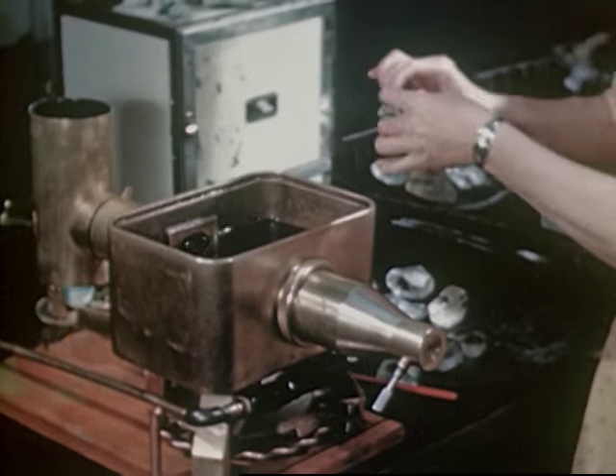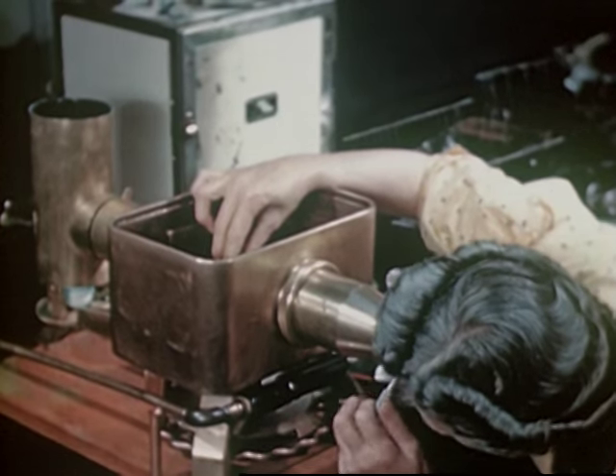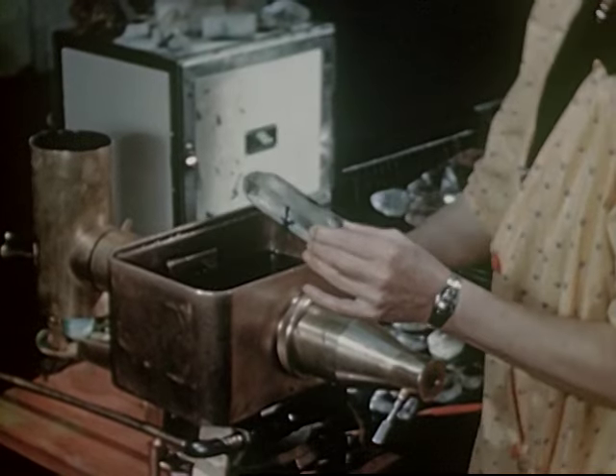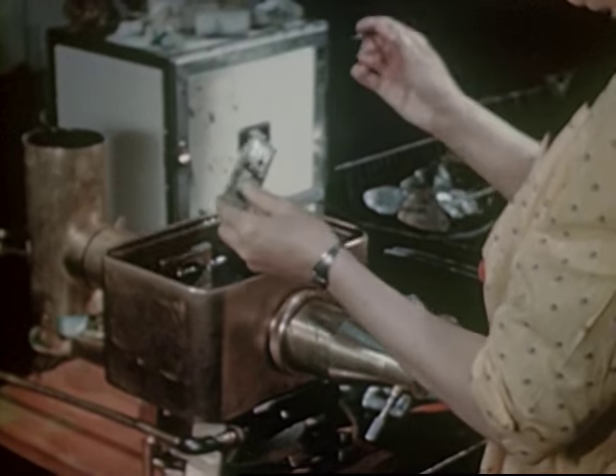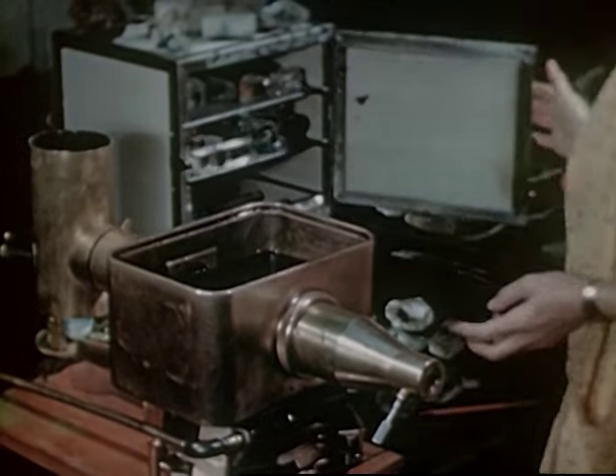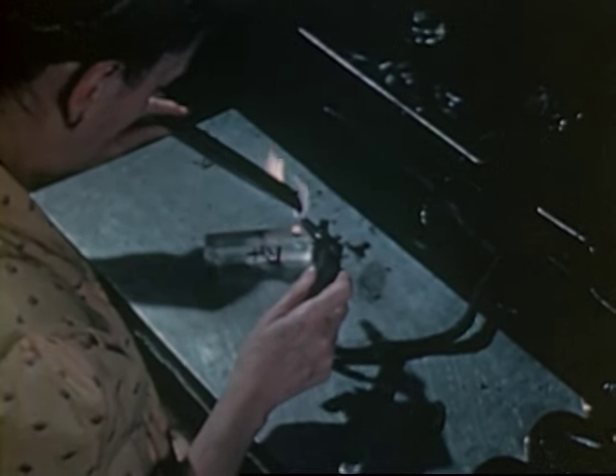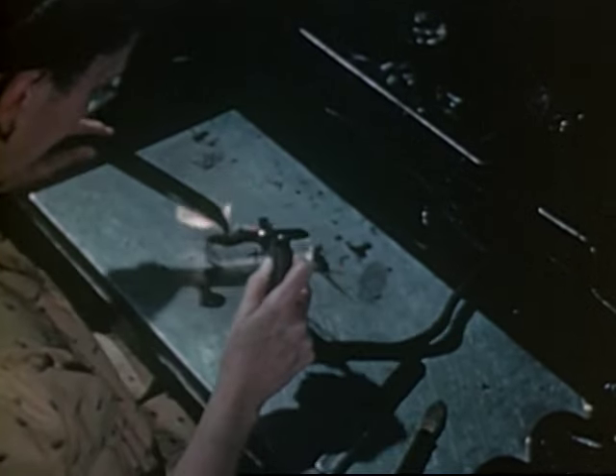The second step in lining up the quartz for cutting is made in a conoscope. Direction marks are again made on the bar, and it is placed in an electric oven to be heated in preparation for mounting. The warmed quartz is taken from the oven, coated with shellac and hot cementing compound, and its piezoelectrically negative side mounted down against the faceplate of the jig.